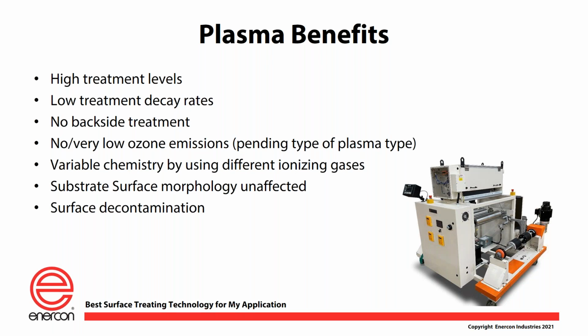The other benefit to these atmospheric plasma systems is that the chemistry can be changed. When you're turning your corona treater on, the air is what the air is. You can't change it. It ionizes the air that's there, and you're good. In an atmospheric plasma treater, let's say we typically run a gas combination of 95% argon and 5% oxygen, and we get a given result. Then we change the substrate or something in our process, and now the treatment isn't quite what you wanted. Well, let's say you reduce the argon by a few percentage points and increase the oxygen a few percentage points. Now all of a sudden you went from a result that wasn't ideal back to a good result. You can't do that with a corona treater. So atmospheric plasma treaters do have some benefit in being able to vary the chemistry that's being used.